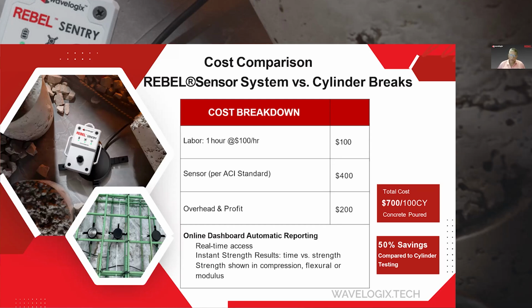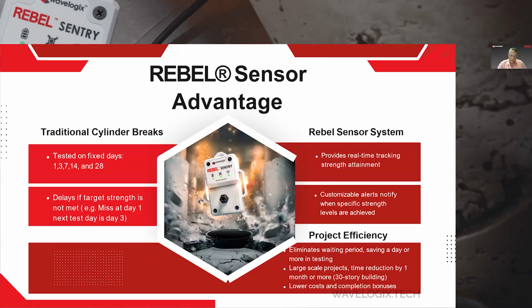So our total cost for deploying one sensor, for an equivalent of the 15 cylinder breaks, would cost about $700. And that's about a 50% savings compared to cylinder breaks. On top of that, you'll end up with real-time access to the strength results of time versus strength. And we can show those results in our system, in compression, flexural, and modulus. So you're getting real data at a lower cost.